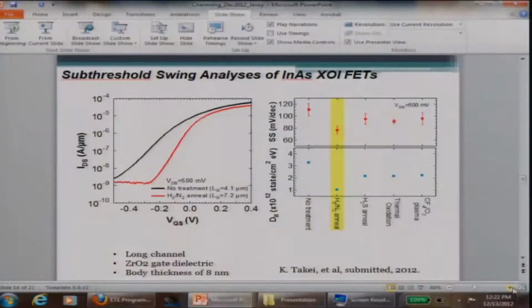The swing here is about 110 millivolt per decade. You do a forming gas anneal. It's a different device, but it's made with a forming gas anneal. And you can see the swing for this particular device is about 72 millivolt per decade at a VDS of 500 millivolt. These are long channel devices, but now we're getting closer and closer to the MOSFET ideal limit of